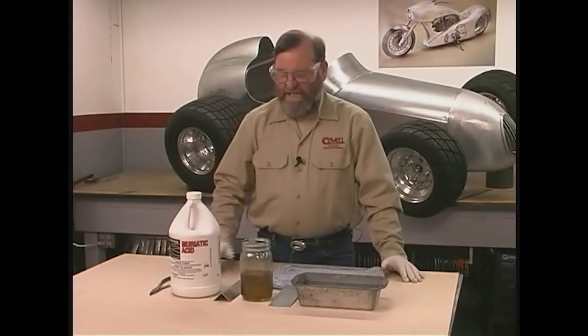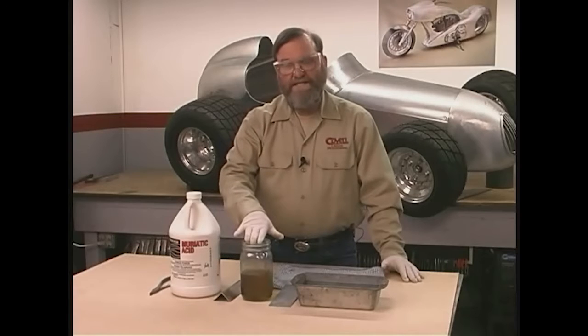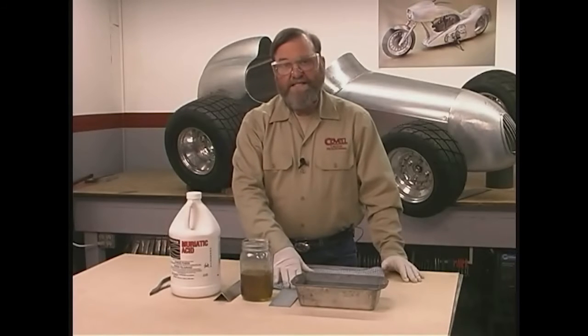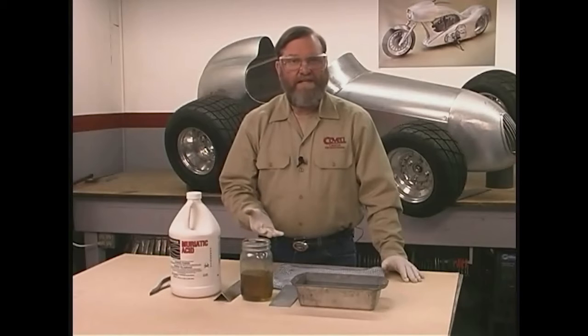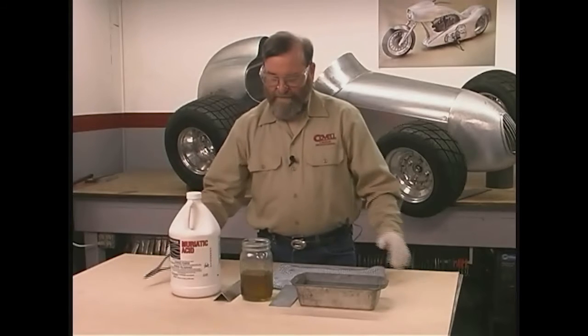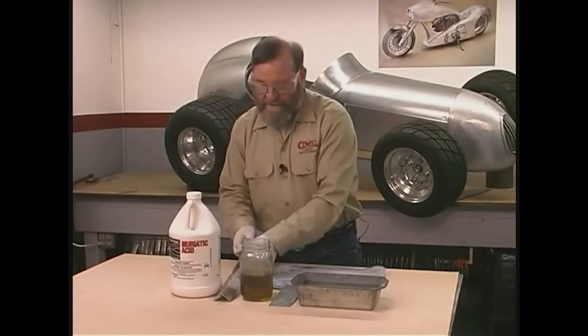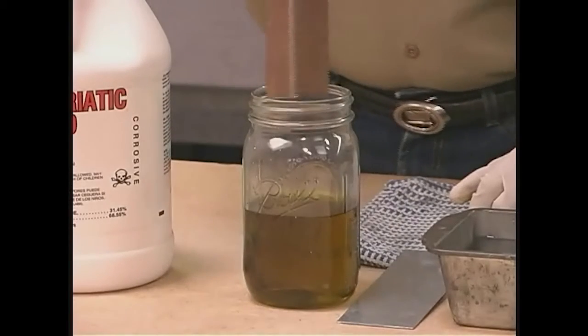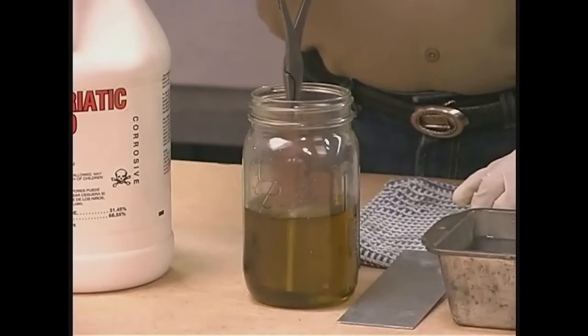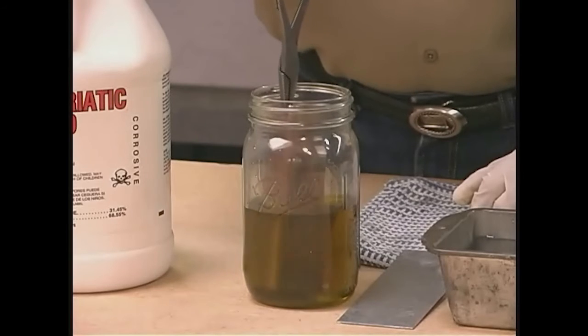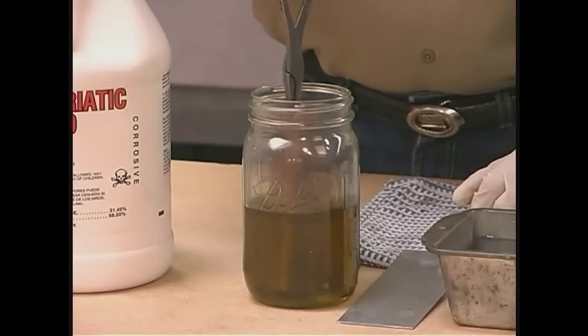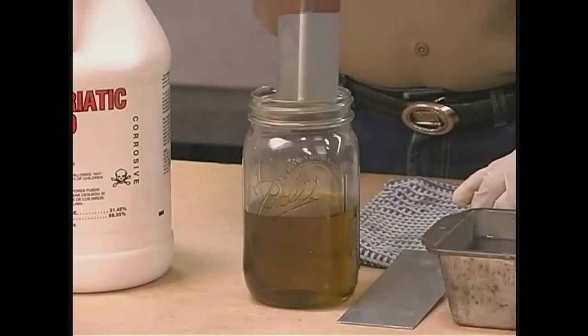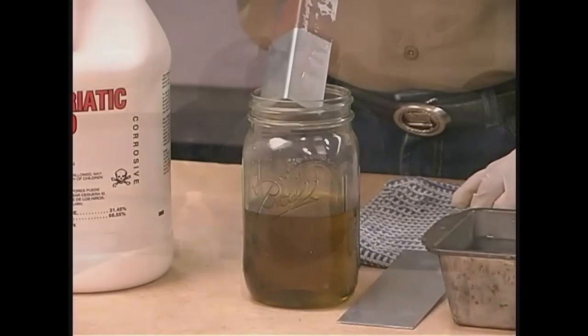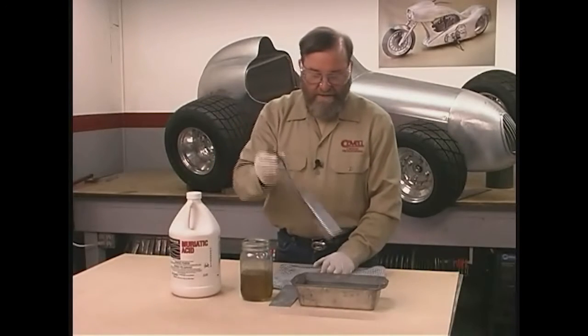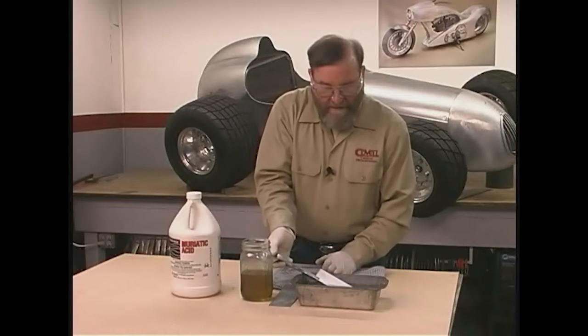But for our demonstration, I'm going to dip first a rusty piece of metal in some acid and then a piece of galvanized steel. And you'll be able to see just how quickly it strips them down to bare metal. So let's do the steel piece first. This can work fairly quickly, but it depends on how rusty the part is. Our test piece has only a light coating of rust, so it should strip that off in just a few seconds. If the rust is very heavy, it might take a couple of minutes for this. And I'll neutralize this acid by dipping the part in water.